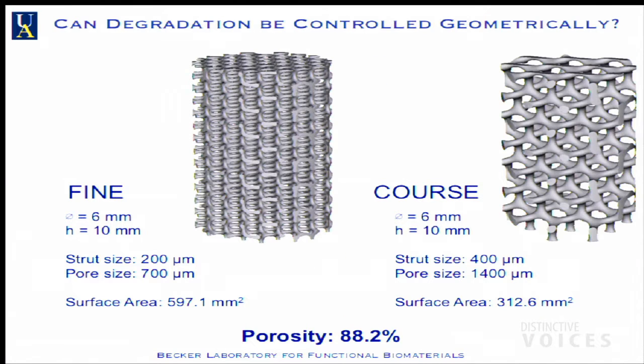I've just got a few slides left. I've got about 10 minutes. So if we look back now at my sheep example, where I said the paradigm for a long time had been, if you want to do tissue engineering of bone, the material has to degrade at the same rate the bone forms. In polymers before, they hadn't really thought about how to do that. But now that we have a polymer that's degradable, with fumaric acid, which is resorbed in the Krebs cycle, and polypropylene glycol, very short chains, even though they're chemically cross-linked, we might be able to control this if we can control geometry.